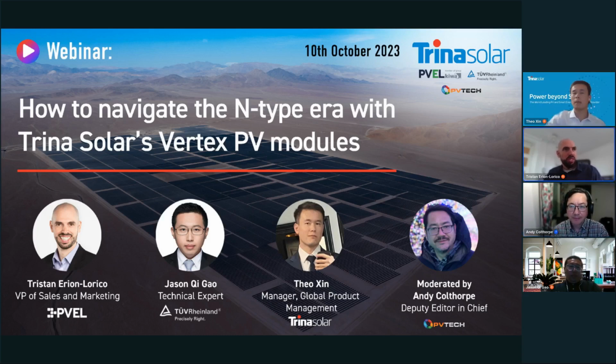Yeah, I've mentioned that a few times. That was specific to the thermal cycling results, which is essentially a cell soldering test. It looks at other things, but cell soldering is definitely part of it. And I mentioned that HJT requires low temperature soldering. If you use the standard soldering for HJT that you would use for TOPCon or PERC, which is higher temperature, you'll destroy the layers on the HJT cells. So you have to use a low temperature soldering process.